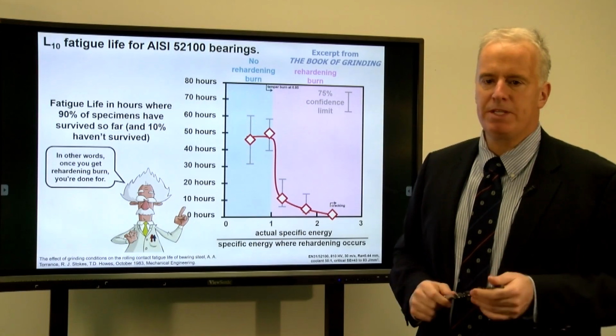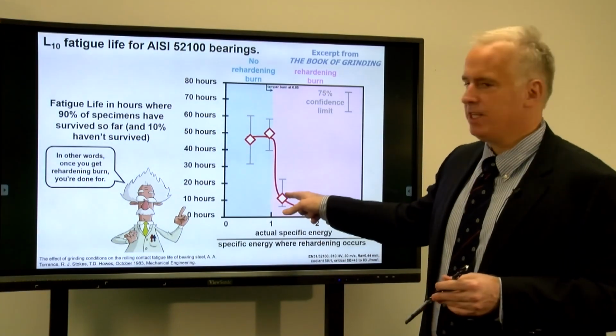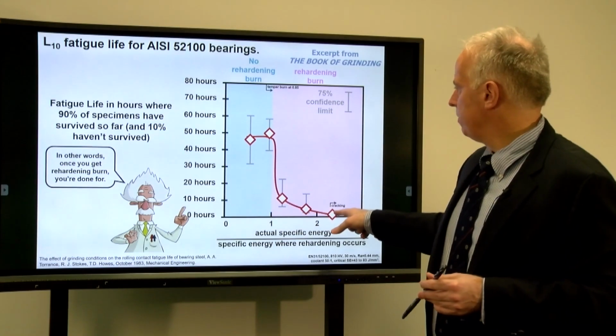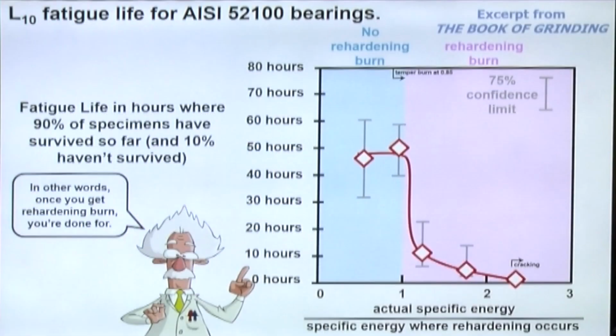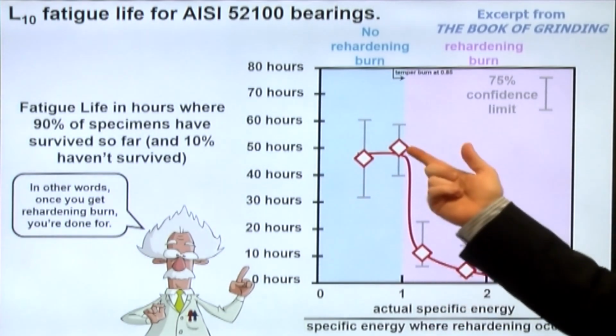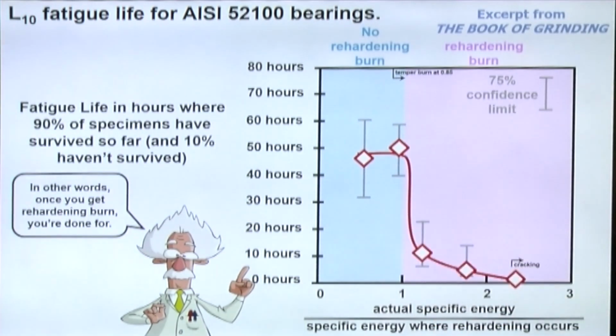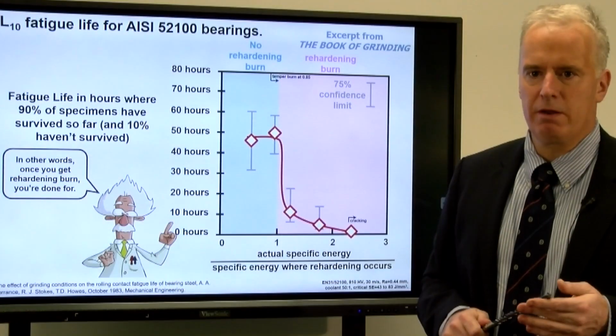And now you've weakened that material so much, it's brittle, and now your fatigue life just goes terrible, down to almost nothing. So the little bit of thermal softening, probably not going to affect the fatigue life much. A little bit of residual tensile stress can affect the fatigue life, but as soon as you get rehardening burn, trouble. And you're going to get a big drop in the fatigue life of the component. Maybe it's a problem, maybe it's not. It depends on how much stress it's under. It depends how many cycles you're hoping to get out of it. But really this shows that residual stresses are bad, rehardening burn, real bad. That's the moral of the story.